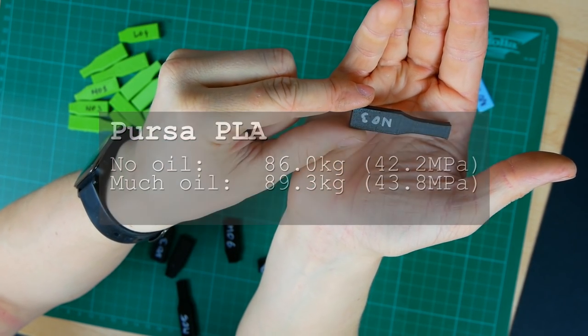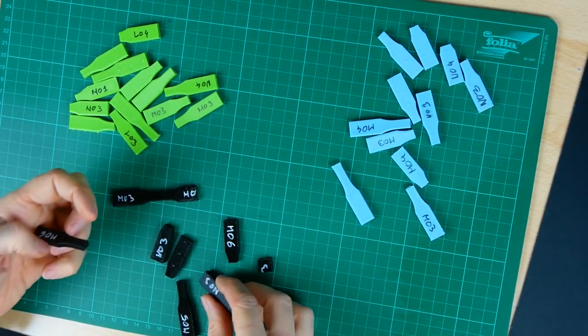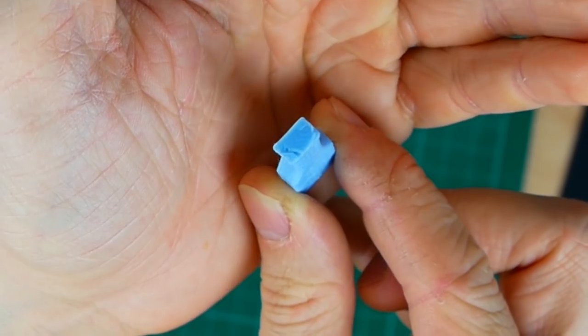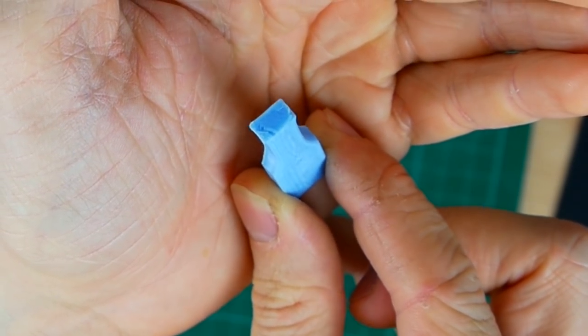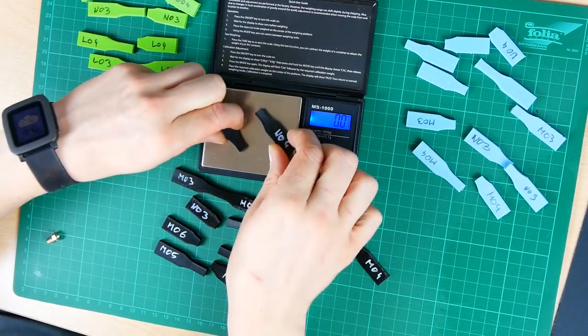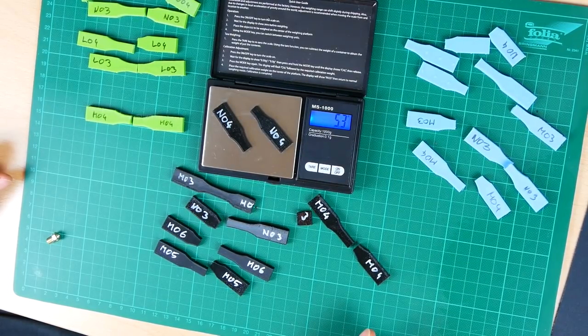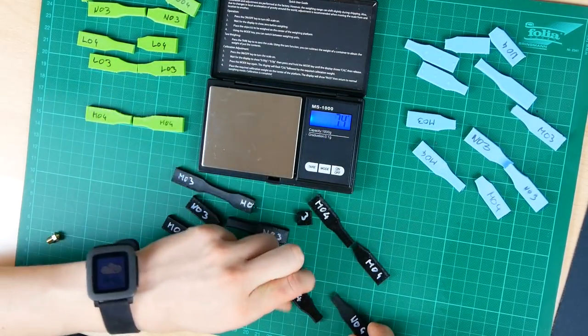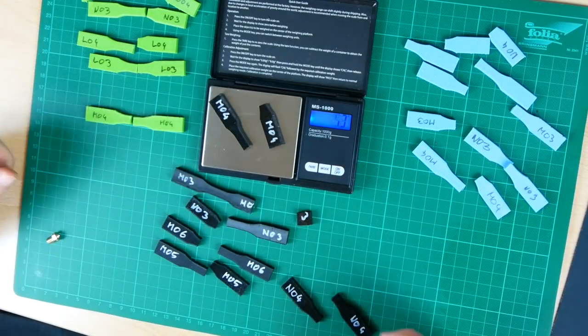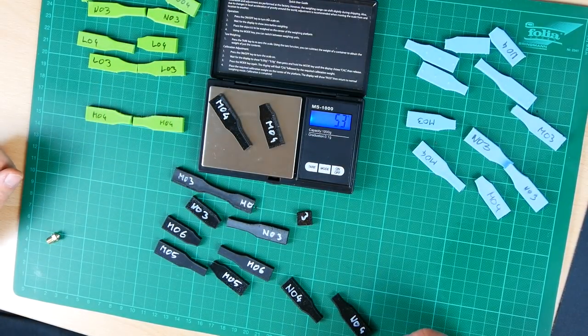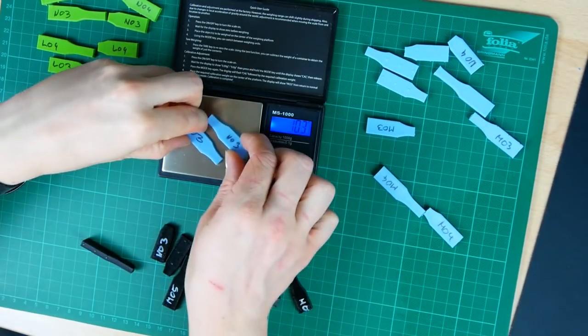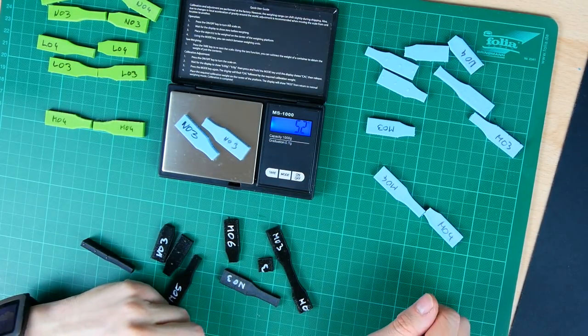Can anyone explain that to me? Why is machine oil bad and the vegetable oil not greatly affecting the results at all? I had seen under-extrusion on some of my broken specimens which were not oiled so one reason might be that the extrusion rate is a little bit higher when oiled. This might result in better layer adhesion. I weighed the specimens but on my scale I was not able to see a difference which would prove that point.